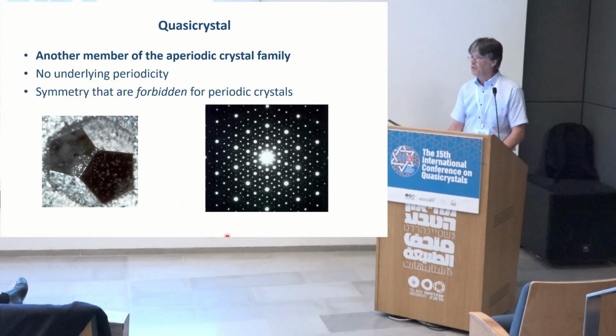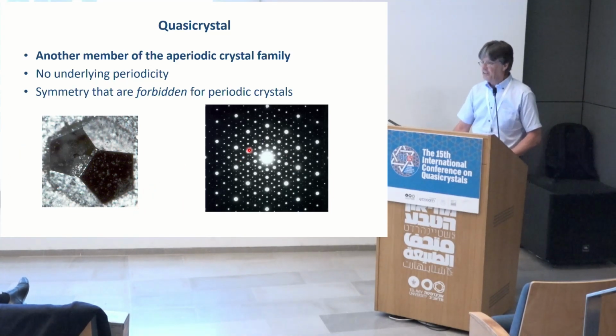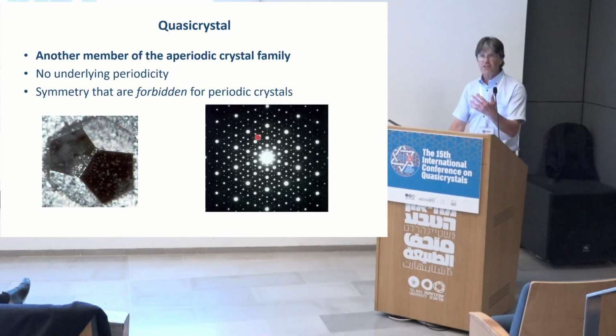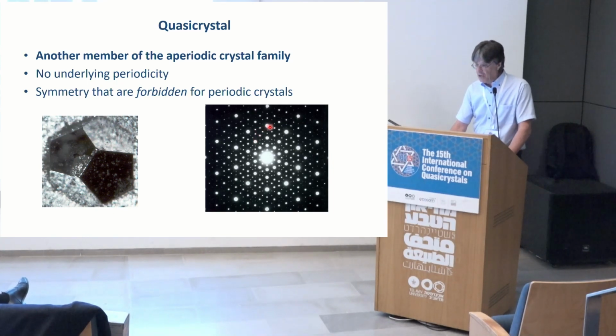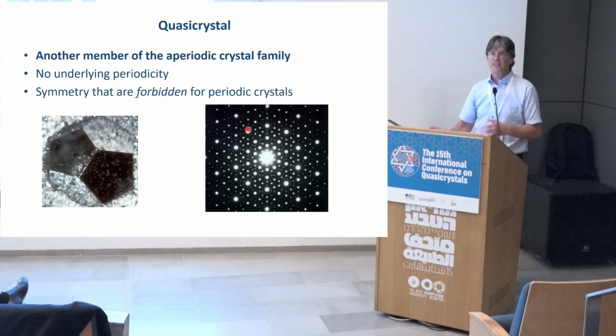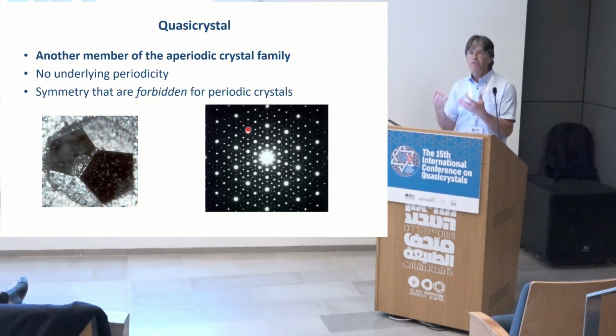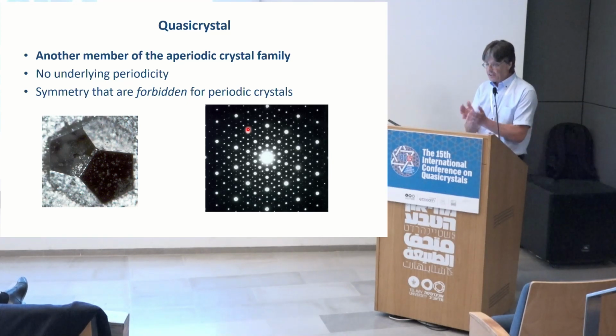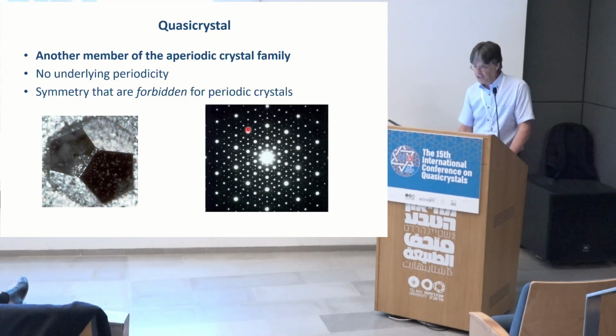This is maybe not the original electron diffractogram by Dan Shechtman, but it's quite similar. It was first observed on rapidly quenched material, and what was striking on those systems is that you have here a tenfold symmetry. So if we start from here, 1, 2, 3, 4, 5, 6, 7, 8, 9, 10. And as I said in the introduction, tenfold symmetry is not compatible with periodicity. So that was already a trace that something strange was going on.